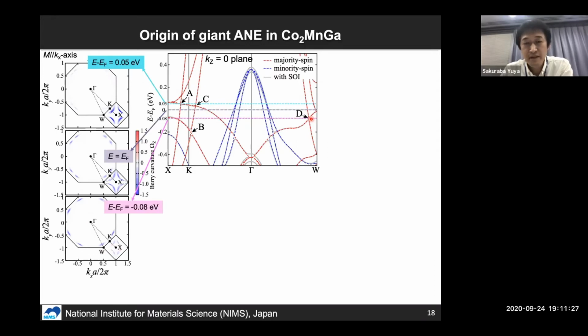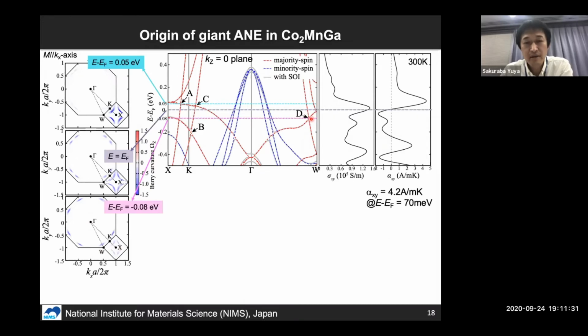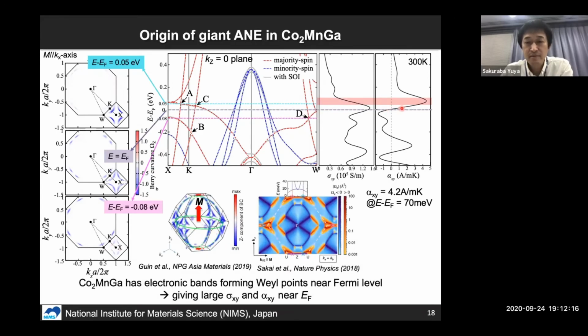And the most important point is that in this material, because of the many band crossing points near the Fermi level, this material has a large intrinsic anomalous Hall conductivity at the Fermi level. But as you can see, when the energy level becomes higher or lower, this sigma xy drastically reduces. So if we calculate the alpha xy based on this sigma xy, we can clearly see the large enhancement of positive and negative alpha xy around the Fermi level. Actually, this large alpha xy is the origin of a large anomalous Nernst effect in this material. This kind of explanation was also given in these previous two studies.